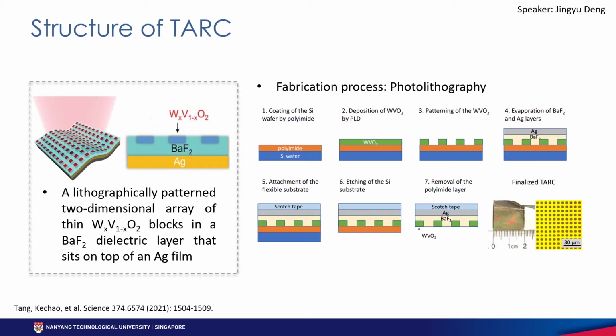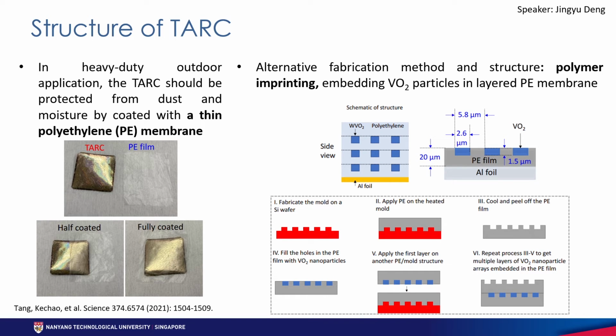I'm going to introduce the structure, properties, and mechanisms of the TARC. The TARC is fabricated by a photolithography process, which is shown in seven steps here on the right side. It has a very special structure: a lithographically patterned two-dimensional array of thin tungsten vanadium oxide blocks in a barium fluoride dielectric layer that sits on top of a silver layer. If we apply the TARC in heavy-duty outdoor applications, the TARC should be protected from dust and moisture, for which a thin polyethylene membrane can be coated on the surface of the TARC, as shown in the figures here. Another alternative fabrication method is polymer imprinting, which embeds the vanadium dioxide particles in a layer of polyethylene membrane.